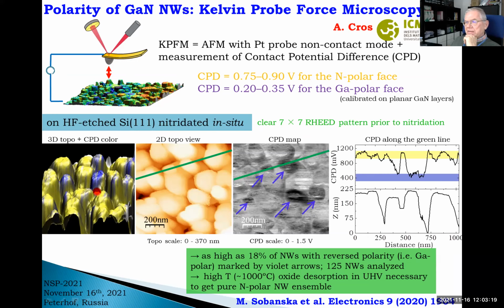But then the result came from Valencia: the distribution of this contact potential difference along wires, and you see that the majority of them are gray, they are nitrogen polar, but there are some of them which are black, and these are gallium polar. In this particular sample, or in general, when we use this procedure, we noted that as high as 18% of nanowires exhibited reverse polarity. So they are gallium polar instead of being, as expected, nitrogen polar.